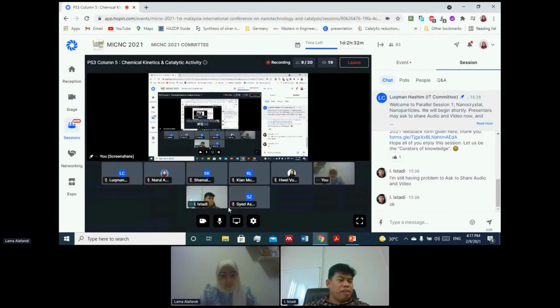What is the role of the doped element on the catalysis mechanism of the silver catalyst? Sorry, again? The role of the component from the coffee extract that doped on the silver catalyst in the catalysis testing mechanism. It's the electron relay effect, because silver nanoparticles will work to donate electrons, so it will activate the methylene blue as a redox catalyst. I hope I answered your question.